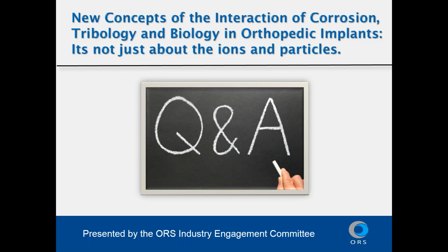Okay, so next question, how do metal ions cause cell necrosis? How is necrosis different from apoptosis? That's a good question. As a metallurgist, I'll do my best to answer it. So necrosis is just essentially cell death. The cells are dying, and in the case of the positive voltage, they're dying as a result of cations coming off of the cobalt chrome surface. I should point out that when we were at 500 millivolts on titanium, we didn't see cell death. So it's due to the ions, and those ions at that voltage have chromium +6 associated with them.